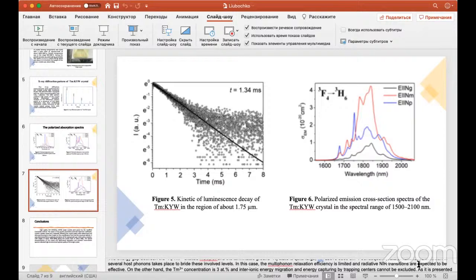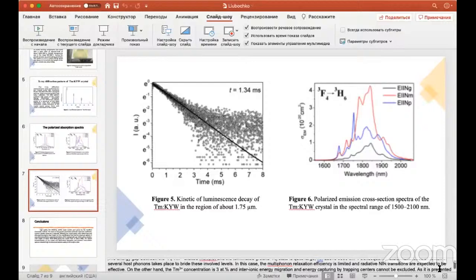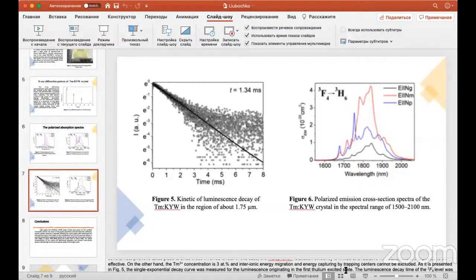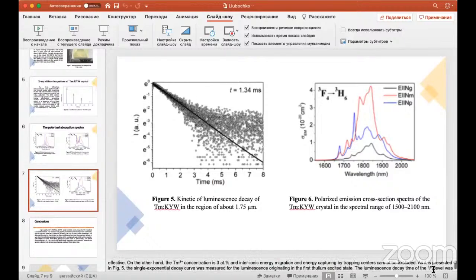On the other hand, the Tm3+ concentration is 3 atomic percent, and interionic energy migration and energy capture by trapping centers cannot be excluded, as is presented in figure 5. A single exponential decay curve was measured for the luminescence originating in the first thulium excited state. The luminescence decay time of the 3F4 level was estimated to be